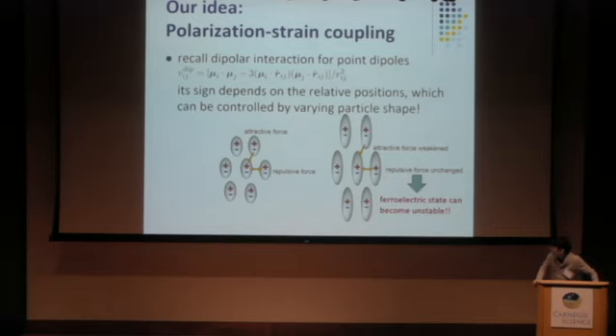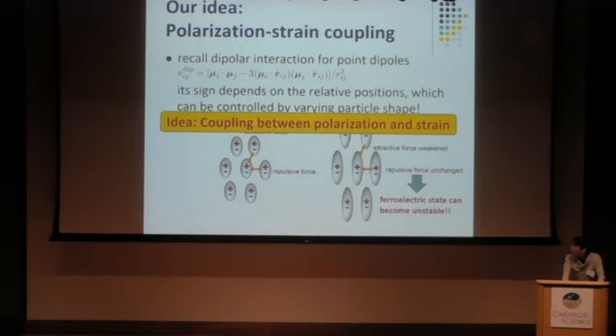in this figure. So suppose we have a ferroelectric state, where the dipole moments align in the same direction. In the vertical direction, the dipole interaction is repulsive, and in the horizontal direction it is attractive. And by changing particle shape or applying stress, we can expect to change or control the attractive force between the dipoles, like in the right figure. So the idea is the coupling between polarization and strain.